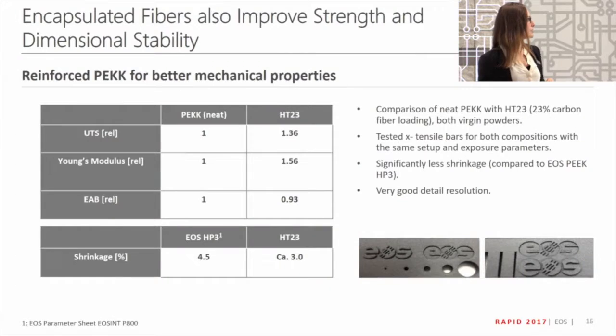So I mentioned the refreshability as another criteria. I don't have any picture on that, but it turned out this PEKK material also is refreshable. We did studies. Usually the powder sees certain damage when it's being exposed to these high temperatures for a long time in the machine. That leads to higher viscosity, and that you cannot always reuse the powder anymore. That's what we had with the current material.